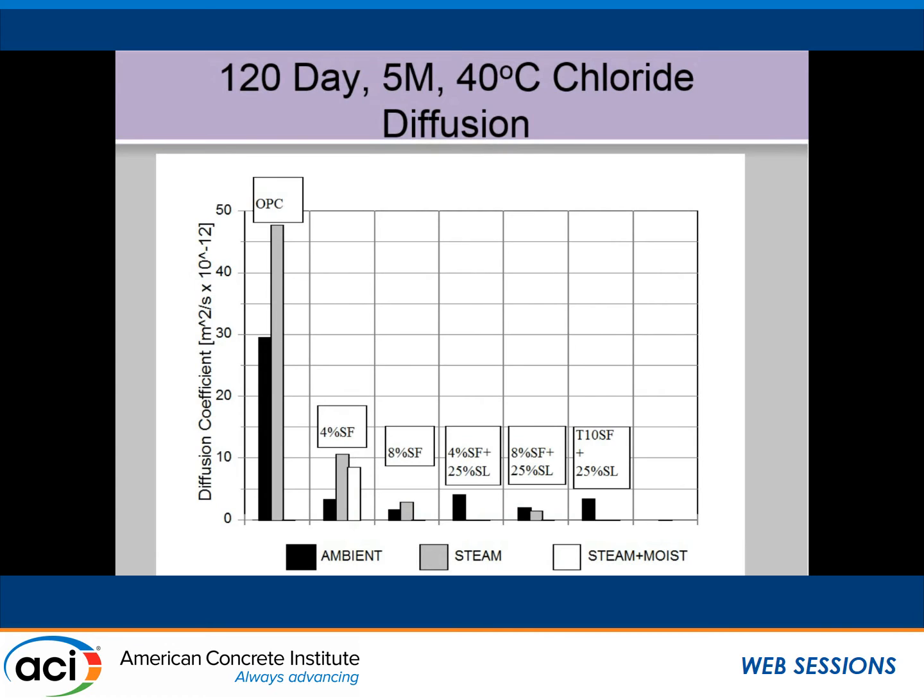In fact, I've just done a study on high-performance concrete for the industry that finished last year, and again, with ternary blends, after the steam curing, we're not seeing the benefit of post-moist curing of those things, which is a big issue because the way the standard is, the precasters don't have the facility to post-moist cure in many cases. The influence of that was very small. So the steam curing with these high-performance mixes is working quite well for them.